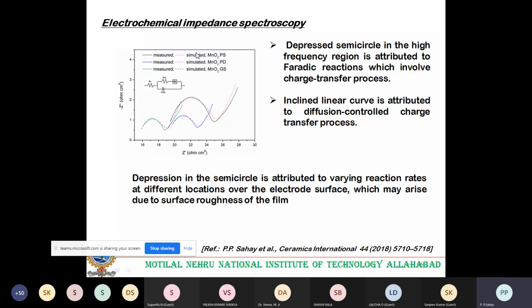We have carried out the EIS study also, that is the electrochemical impedance spectroscopy study. In this study, basically what we do, we plot a graph and we call this graph the Nyquist impedance plot. This is the frequency dependent profile. Here this is the real component and this is the imaginary component of the impedance. The left side is the higher frequency. If you move from left to right, you will see that frequency decreases.